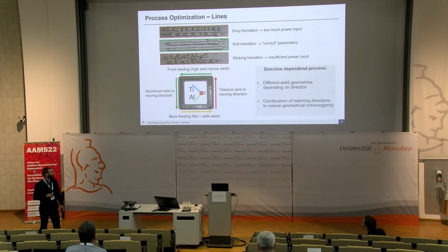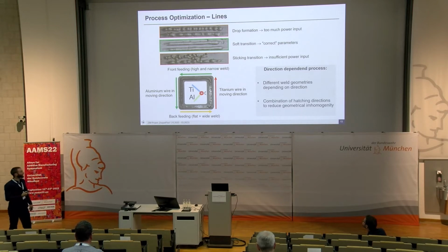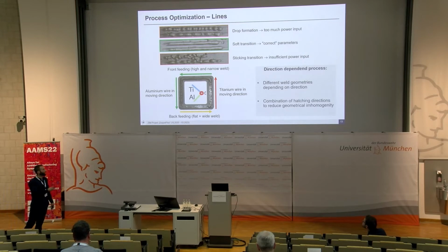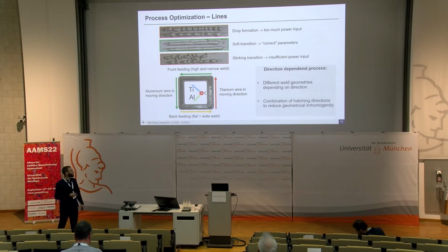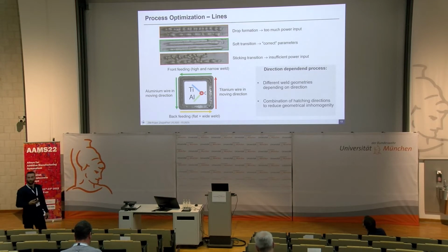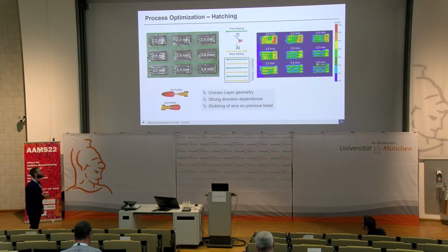But that's not all. With our 3-axis CNC machine, we have a direction-dependent process. If we look at the different directions we are feeding the material, with front feeding we have a really high and narrow weld, and with back feeding we have a flat and wide weld. So that's another complex thing we have to keep in mind. We need a combination of different hatching strategies to reduce these geometrical inhomogeneities.